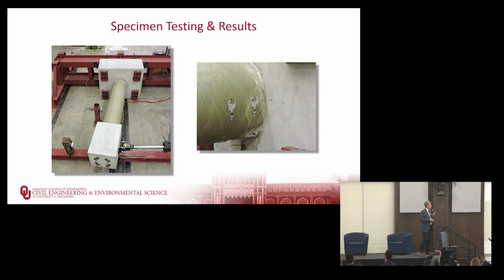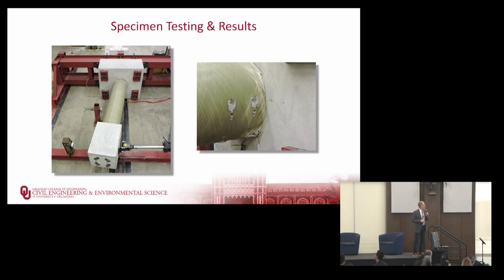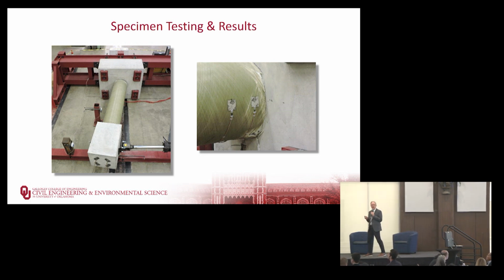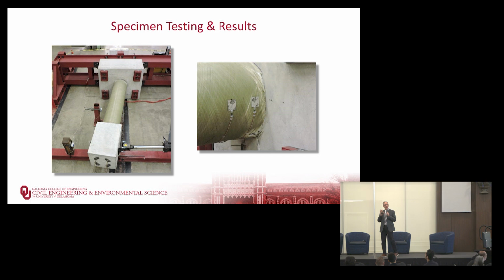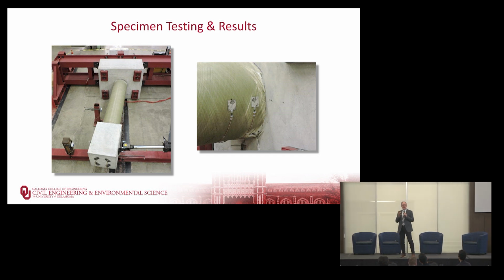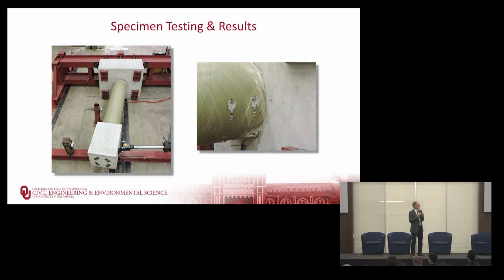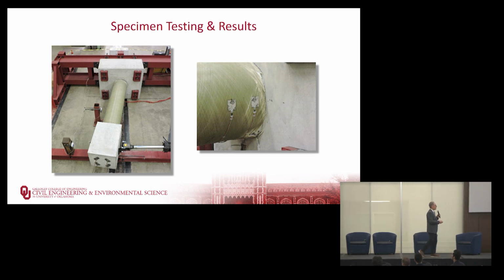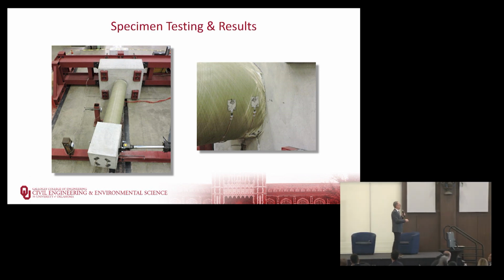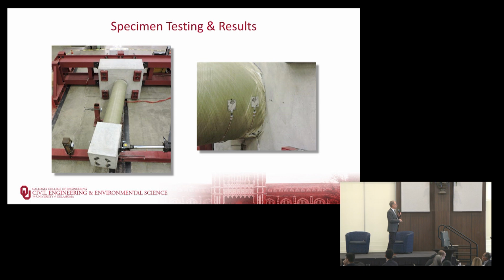So then this is the one with the self-consolidating concrete, high strength. You can see looking down how much we're pushing it over with our actuator back and forth. This is close to failure for the column. You see the FRP tube, you see these white marks. This is the FRP tube starting to snap, the fibers in the FRP starting to snap, exceeding its hoop stress. Remember, it's providing confinement to the concrete, so it increases the apparent strength of the concrete, and it's starting to fail. And just remember how far this comes up in terms of the failure of the FRP.